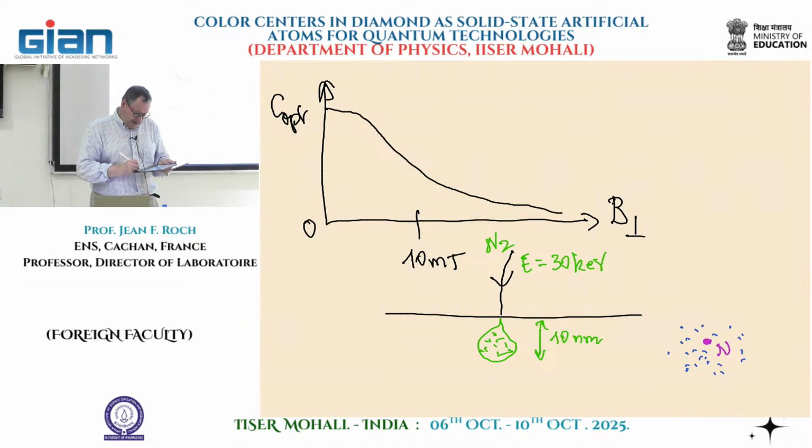The problem now is when you anneal, all those vacancies will move, but most of them will actually go to the surface if you are close to it. And once they are at the surface, they are trapped. So you have a kind of balance. Either you work at low energy, but at low energy, recombination with vacancies will be mostly inefficient, which leads to a very low yield, only below 1%.